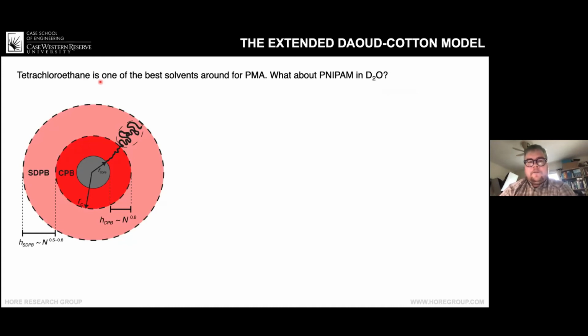But it's a great solvent, and it's one of the best solvents around for PMA, which meant that at these different temperatures, we wouldn't necessarily expect such a huge change in the conformation of the brush, because it's such a great solvent that we wouldn't expect much change in the region of temperature that we could access. On the other hand, PNIPAM in D2O, we know that it has LCST behavior, and we know that that critical temperature is around 32 degrees.